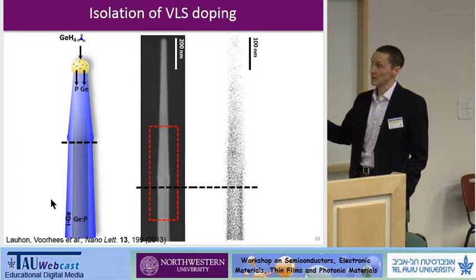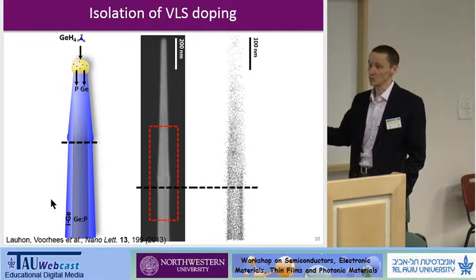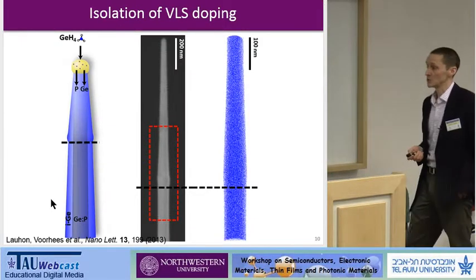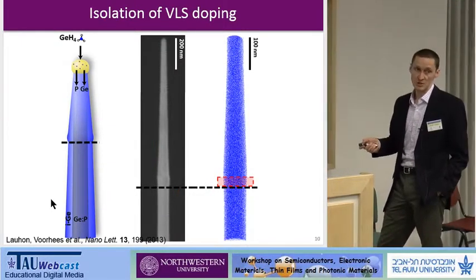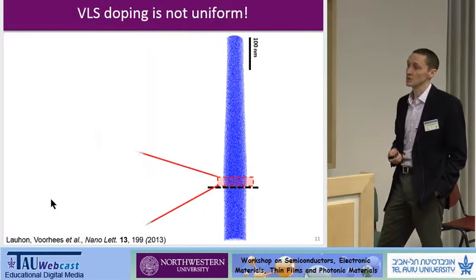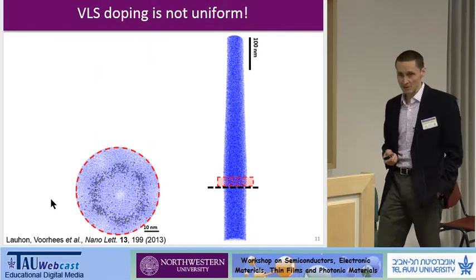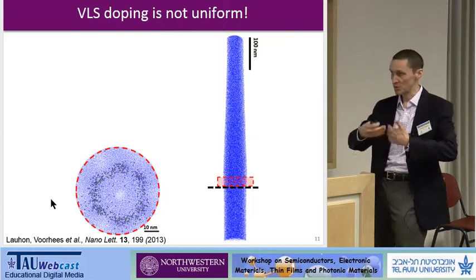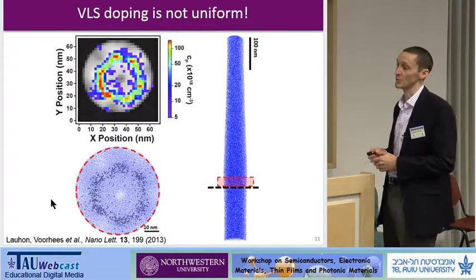You can see it sort of decays past that point because this is just what's coming out of the catalyst. And the surprise to us is when we looked at this region here, after removing the dopant source, we got something that was highly non-uniform. We sort of expected uniform precipitation out of the catalyst. That's not what we saw.